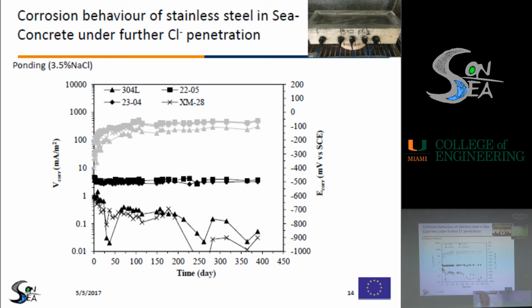So next steps will be to evaluate the chloride content at the depth of the bar reached after 1 year of exposure, in order to compare the chloride content that we have now at the depth of the bar to the chloride content which is expected in a real structure after maybe 50 or 100 years of exposure, in order to investigate whether, under further chloride penetration, stainless steel bar can be used in combination with sea concrete.